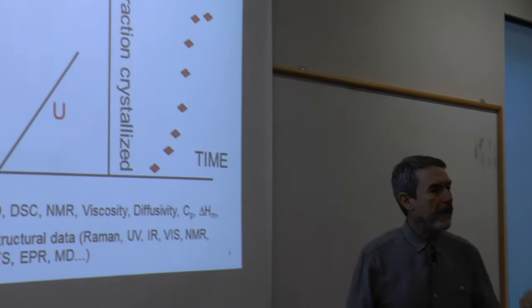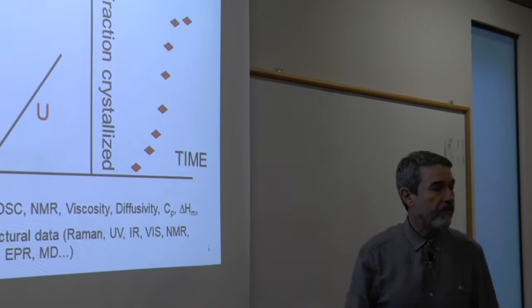Viscosity measurements are needed to calculate these curves, diffusivity, CP, density. You can, for instance, get this curve by measuring the density of the glass and of the partially crystalline materials and the density of a fully crystalline material. By measuring density, you are able to find this kind of volume fraction crystallized. So there are many, many techniques. Okay,